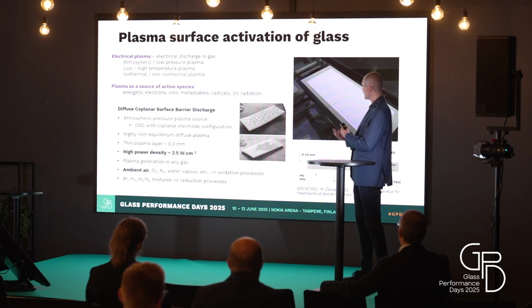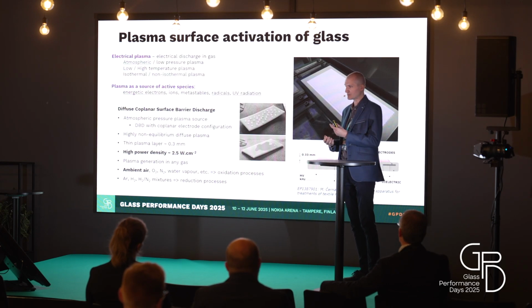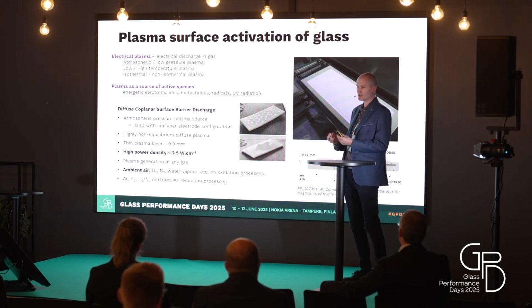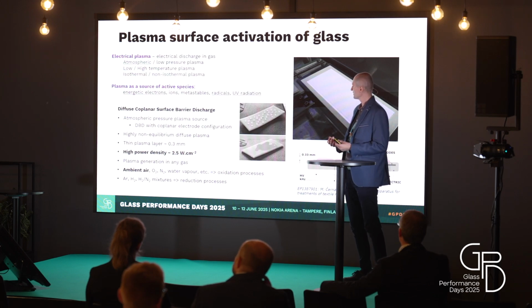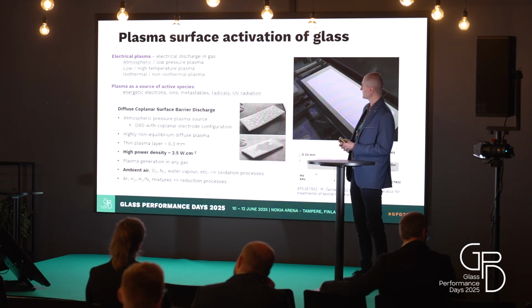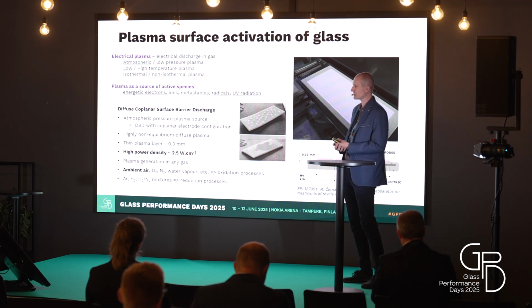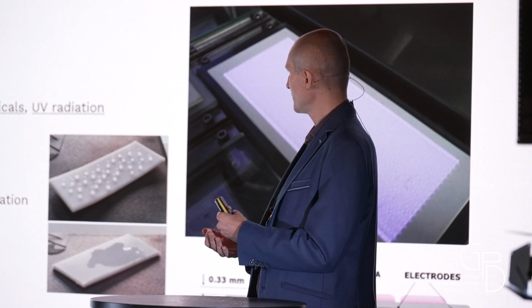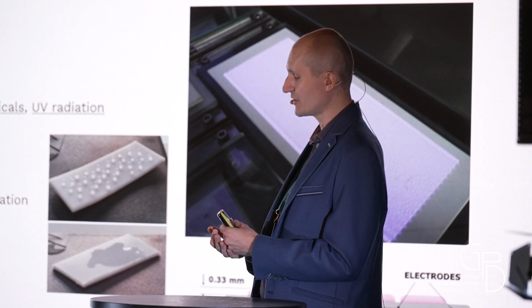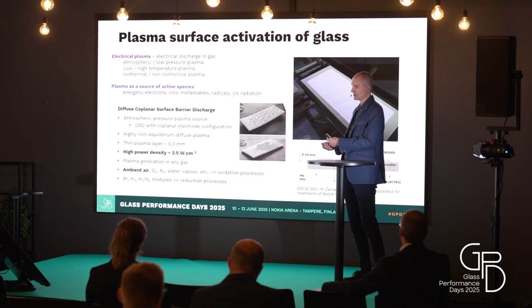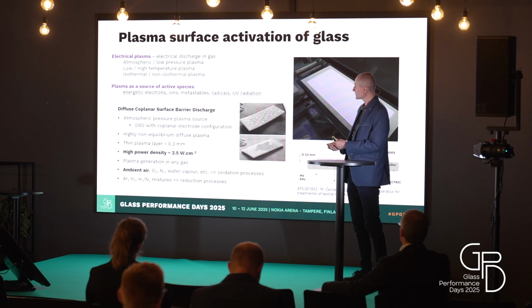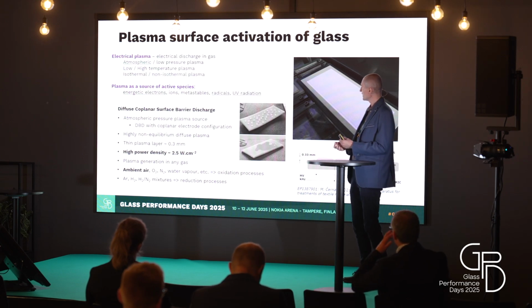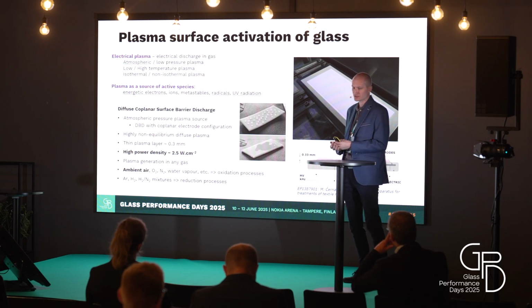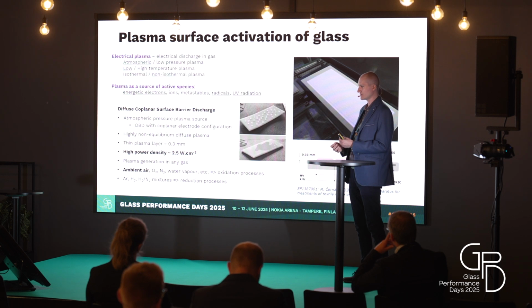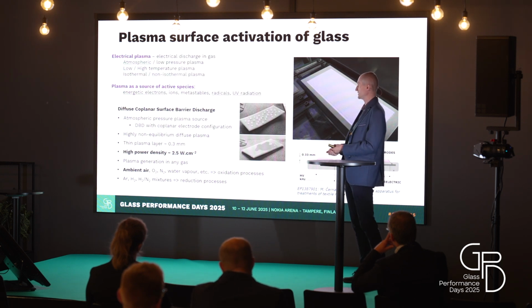And in this slide I would like to introduce this type of plasma in very few words. But first, what plasma is. Basically, plasma is the ionized form of gas where various energetic species are present, like electrons, ions, metastables, radicals, for example. But in our particular case, we are generating plasma at atmospheric pressure where we have low energetic heavy particles, like ions and atoms, but very high energetic electrons, very light particles, and together with the radicals, UV radiation, and metastables, we can introduce this to the surface and initiate some plasma chemical changes on the surface of the material.